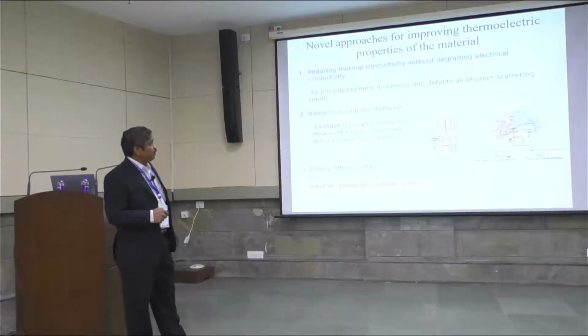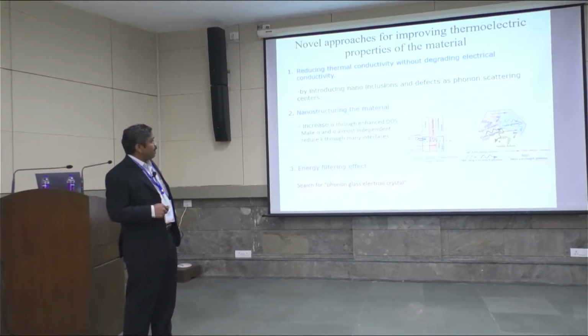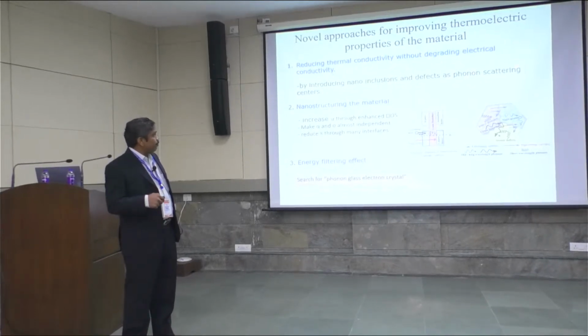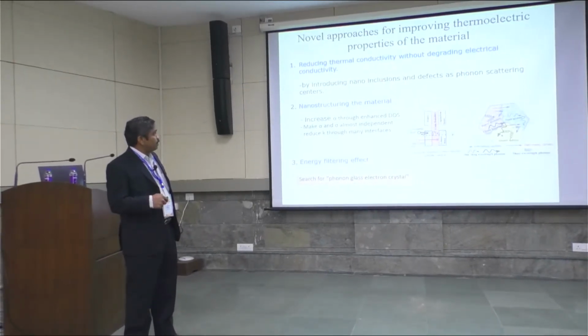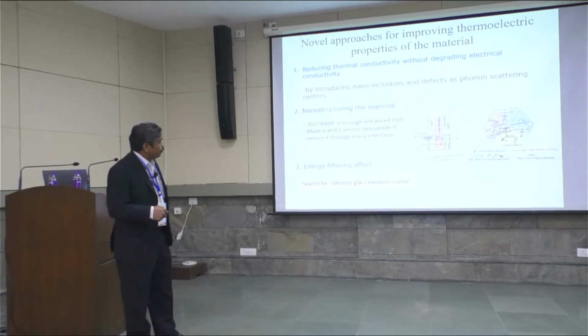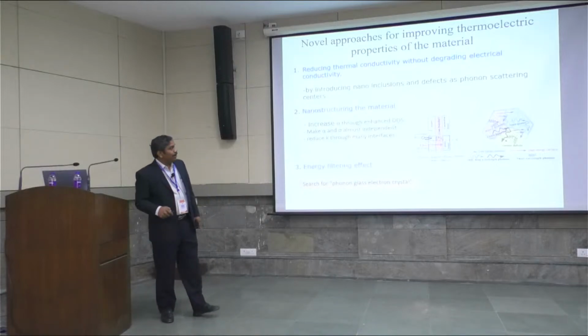Okay? So these are the approaches that people are trying to follow to improve the thermoelectric performance of the different materials. The one thing is reducing the thermal conductivity without degrading the electrical conductivity. And that can be possible by nano inclusion or nano defect engineering to improve the scattering process so that you can control the lattice part of thermal conductivity. And the nanostructuring of the material will help to tune the DOS of the system so that you can independently control the Seebeck as well as the electrical conductivity of the system.